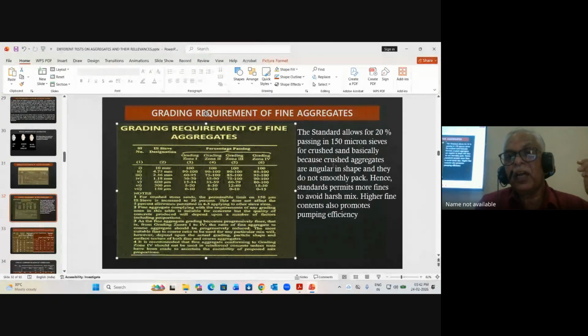Basically because crushed aggregates are angular in shape, they do not pack smoothly inside the concrete. River sand is generally round, so it fills up the voids very easily, whereas crushed sand is angular in shape and will not fill as well. That's why the code has permitted use of a little extra sand so that there's no gap in the final particle packing in the lower sieve sizes. It also helps in raising the 150 micron percentage of fines, which helps in pumping of concrete.